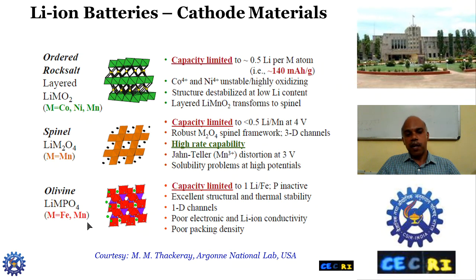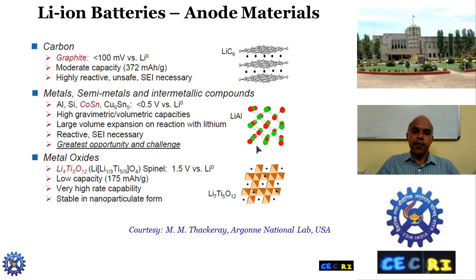And the olivines, LiFePO4 or LiMnPO4, show a very stable structure. For example, in LiFePO4, if you remove lithium, it converts to FePO4, which is also stable, and it goes back to LiFePO4 during discharge. The problem with this is the poor electronic and lithium-ion conductivity, which can be improved by coating with carbon materials. So there are a lot of opportunities available to develop various cathode materials. Similarly, on the anode side, carbon, that is graphite, has been used as a stable anode for lithium-ion batteries. Other materials like silicon, tin, cobalt tin alloys, or intermetallic compounds like copper tin have also been established.